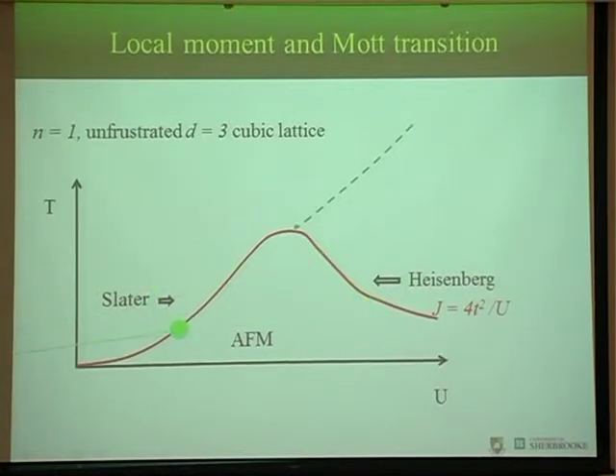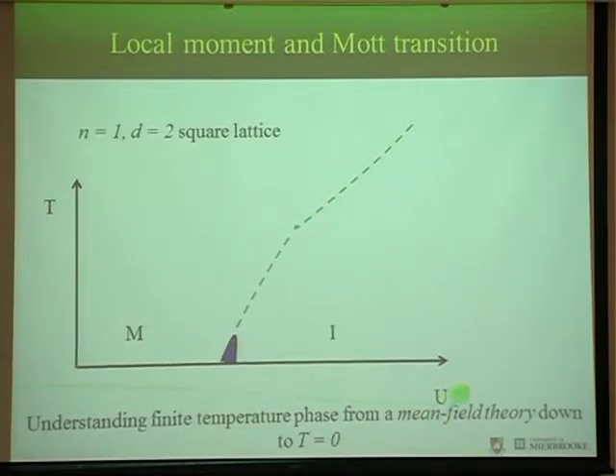If you think of the pressure dependence as modifying the ratio of T over U, then pressure would be moving to the left on this diagram. And you see that the pressure dependence of the Néel temperature is quite different depending on whether your magnet is weakly or strongly correlated. And this line is the Mott phenomenon. In other words, you want to go from something that looks metallic to something that looks like a local moment. It's a non-trivial crossover that is best described by dynamical mean field theory.